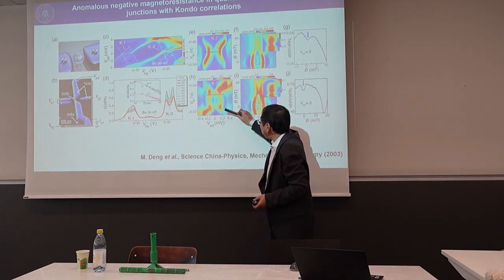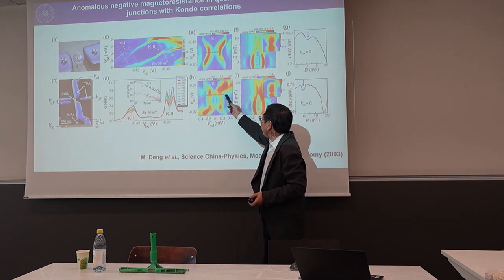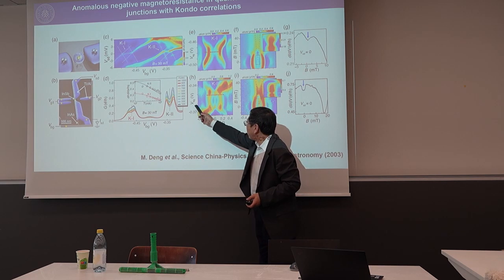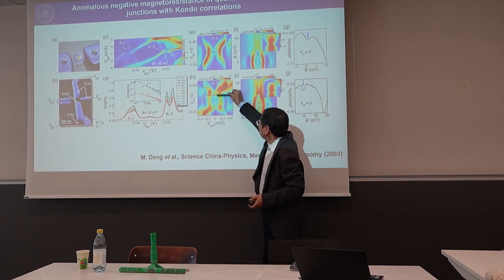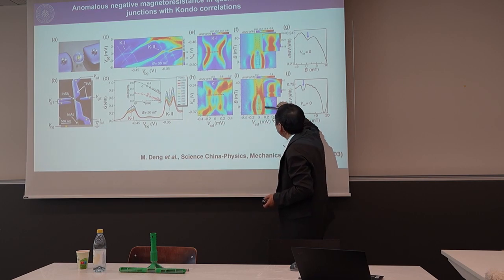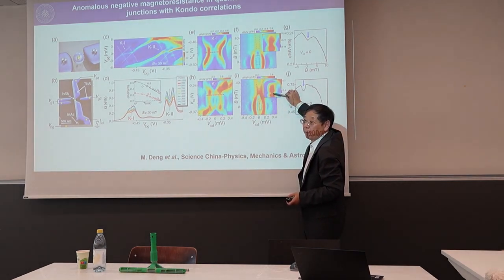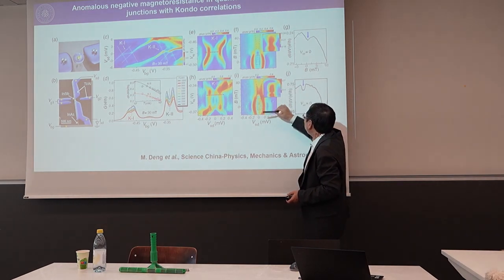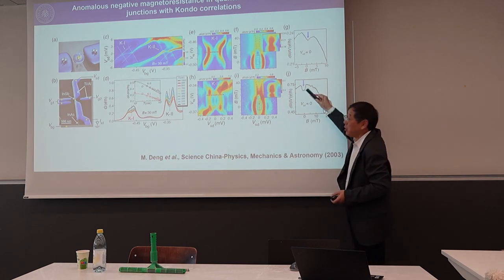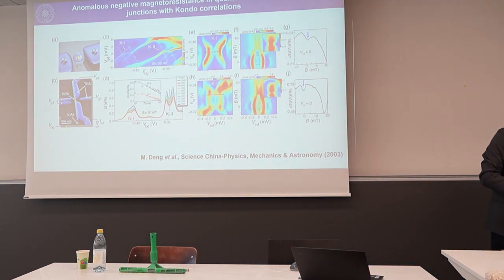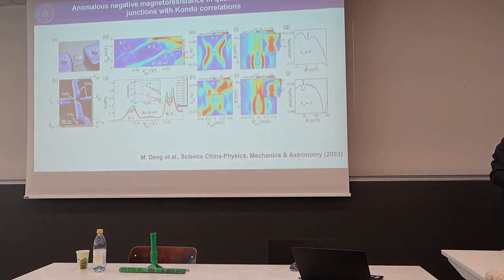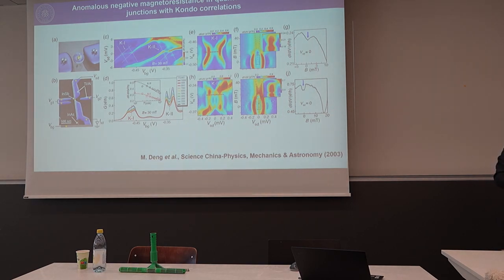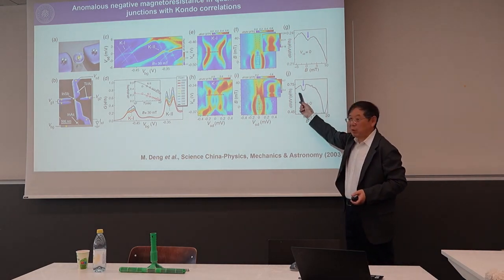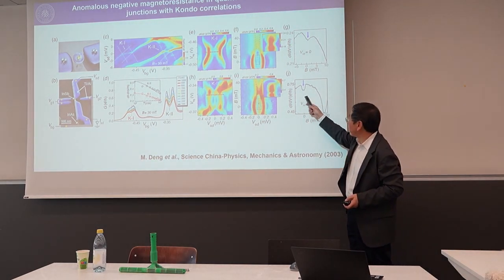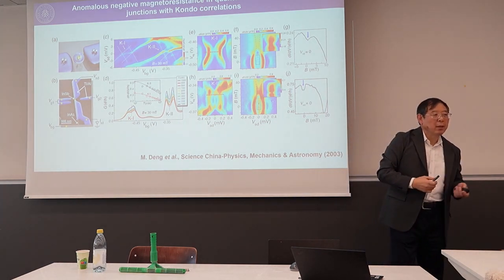And here also. But the problem is, when you fix this line, at this source-drain voltage and this back gate voltage, and then scan the magnetic field in this direction, you see at zero magnetic field very little conductance, and when you increase the magnetic field, the conductance increases. If you cut the line this way, you see this dip. Originally we believed this dip is due to this zero-pi phase interference effect. However, it's very hard for theorists to give us simulated data for that. So we're still waiting for the theory to give us a solid simulation to show it. We didn't get that yet. So that's why.